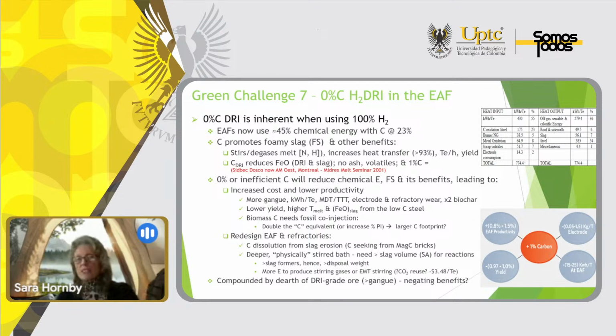So the zero carbon or inefficient carbon use is going to reduce the chemical energy, foamy slag, and its benefits, and it will lead to increased cost and lower productivity. There'll be more gangue, more kilowatt hours, higher meltdown times, greater electrode and refractory wear, and it will use potentially twice the amount of biochar. And we'll get lower yields.